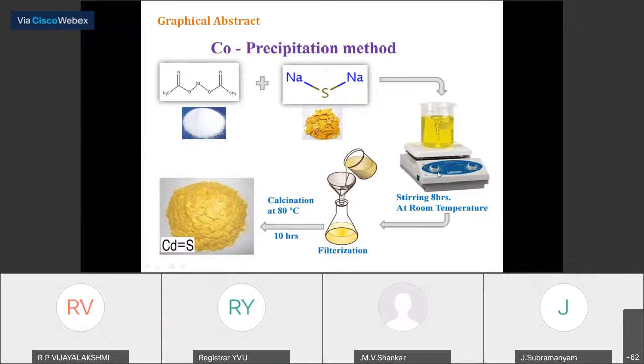Then on a magnetic stirrer, we stir it for about 8 hours. Then we have the reaction, and we get the precipitation. Then we filtered it, and then it was calcinated. To get homogeneity and to remove the water present in the material, we heated the material at 80 degrees centigrade. Finally, we obtained the cadmium sulfide powder. Like this, we can get a variety of powders by using the precipitation method.